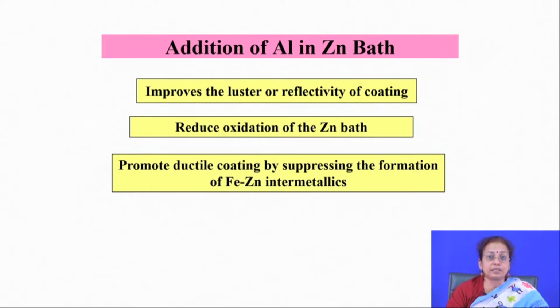If you add aluminum, naturally it serves several purposes. First of all, aluminum improves the oxidation resistance of this bath. Second, there is formation of an iron aluminum intermetallic at the interface, as a result of which the zinc cannot form any kind of intermetallic with iron. So, it prevents the formation of iron zinc intermetallics by forming a very thin layer of iron aluminide on the surface. And the third purpose is that it increases the luster of the coating. Whenever you add aluminum, you will find that the coating is highly lustrous.